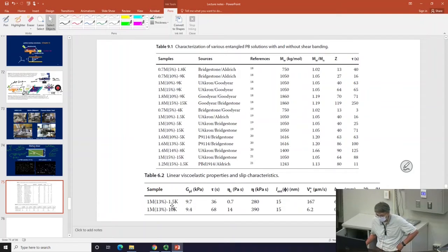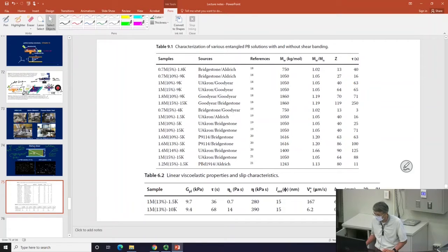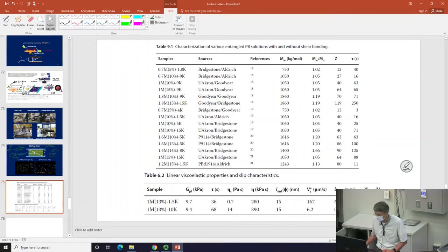All this means we had to prepare a bunch of samples. These tables list samples mainly in the 5 to 15% concentration range with very high molecular weight so that you have enough entanglement even at 10%. We even have two more samples where the concentration is fixed but we change the molecular weight of the solvent — using 1.5K versus 10K polybutadiene as the solvent. The maximum slip length B inversely depends on solvent viscosity, so one could reduce B by a great deal by using a very viscous solvent — parameters changing by more than a factor of 10.